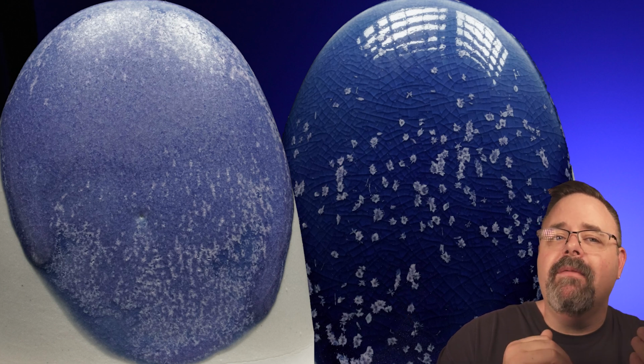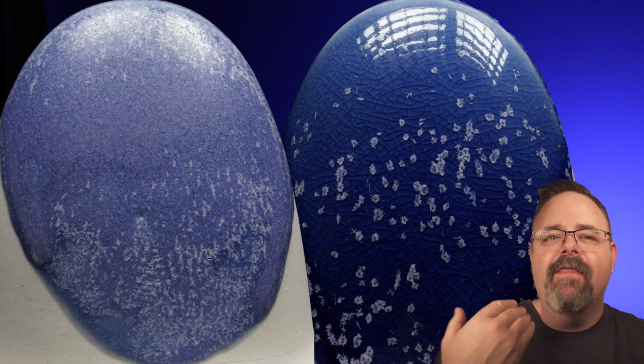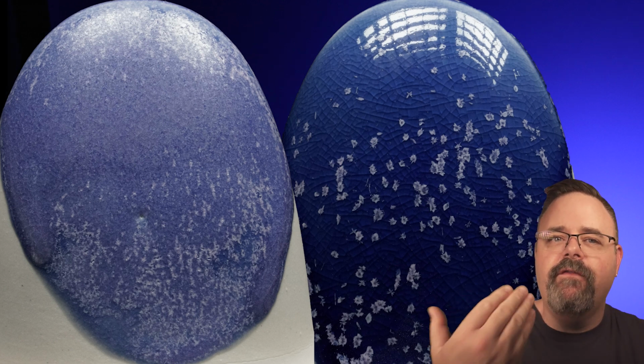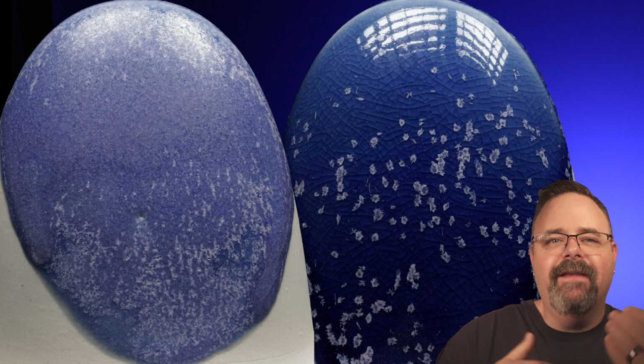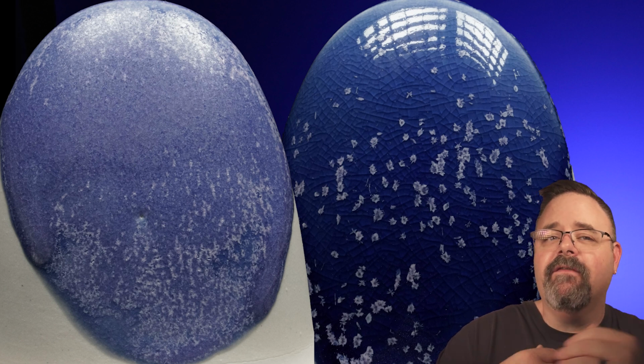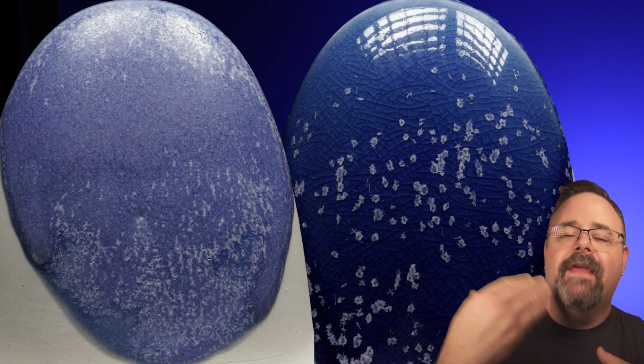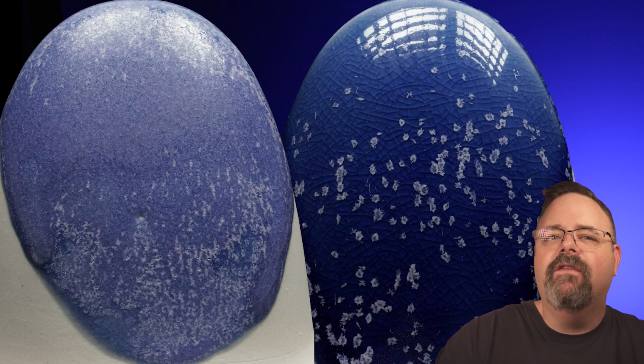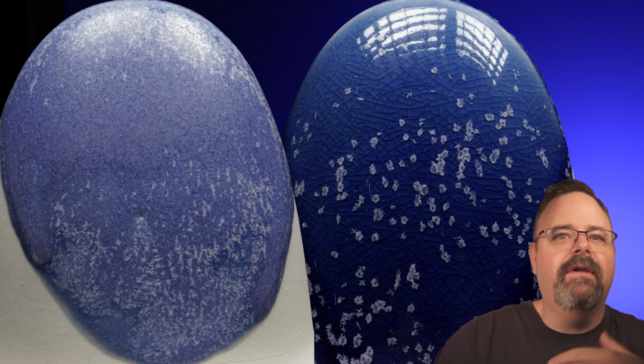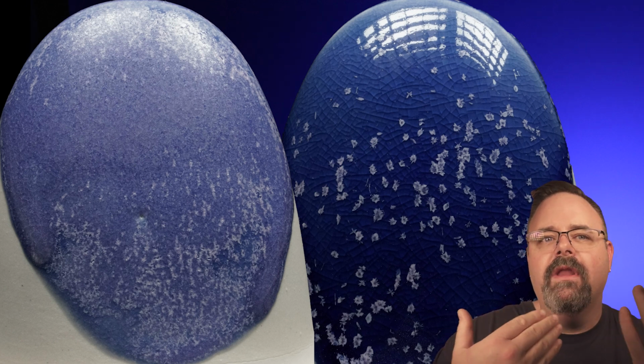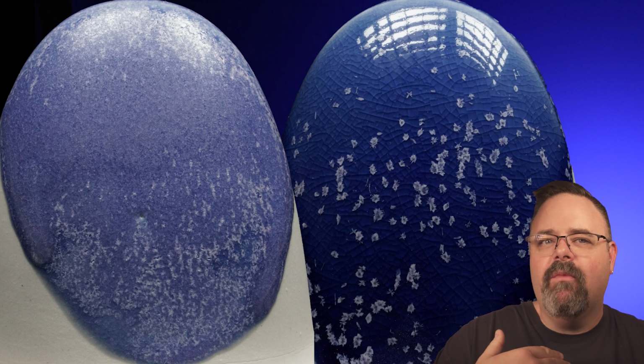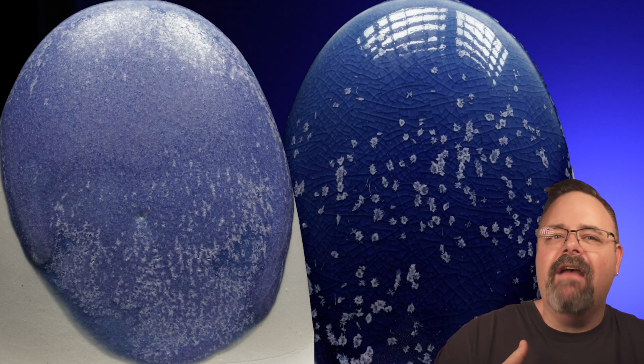The bigger problem that it makes is that the colder you fire a crystalline glaze, the more crystals are going to form. And the hotter you fire a crystalline glaze, the fewer crystals are going to form. And this can create a big problem when your basic firing temperature is colder than what most of the world is firing to. So there are a ton of glazes in the UK and in the EU that are only being fired to cone 8 that many people will call matte glazes. They most definitely are not matte glazes via chemistry. They are crystalline glazes that are over-nucleating.